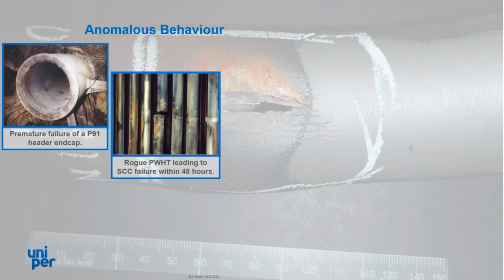Post-weld heat treatment has also not always been ideal. Somewhat cavalier approaches taken by contractors has led to hardnesses in excess of 400 Vickers relative to the expected values of around about 200. In this particular example here, in an evaporator tube, we saw a stress corrosion failure. I've put 48 hours. The reality is that the failure probably occurred in a 7mm thick component in the space of 6 to 7 hours. So it can be very rapid if you get things wrong.